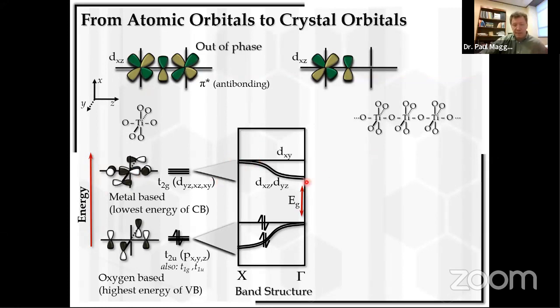Now, as you go from X to gamma, what happens though is that the nodes between the orbitals decrease, such that when you reach the gamma point, there is no node here between the d orbitals, and they stay the same phase, going from one titanium to the next titanium. And now at the gamma point in K space, as you can see here, the p orbital does not have the appropriate symmetry to interact with either of the d orbitals. And so it becomes a node. There's no interaction between that oxygen p and the titanium d. And so that lowers the band here and makes the crystal orbital non-bonding at this point in K space.